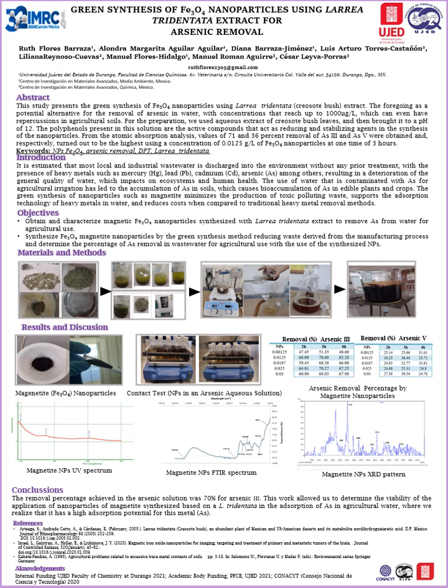X-ray diffraction of the nanoparticles was characterized in a Philips X'Pert MPD diffractometer equipped with a graphite curved monochromator with a copper anode that has a lambda of 0.154056 nanometers. The magnetite has average crystalline sizes equal to 26.32, 43.86, and 104 nanometers respectively, according to the Scherrer equation. Furthermore, it is found that all the reflection peaks at 220, 311, 400, 422, and 511, as well as the 440 planes, are related to the inverse spinel cubic structure of the magnetite nanoparticles.